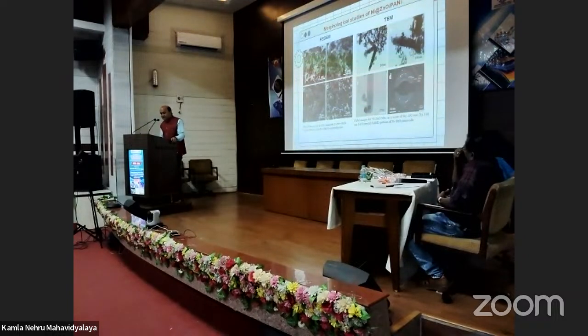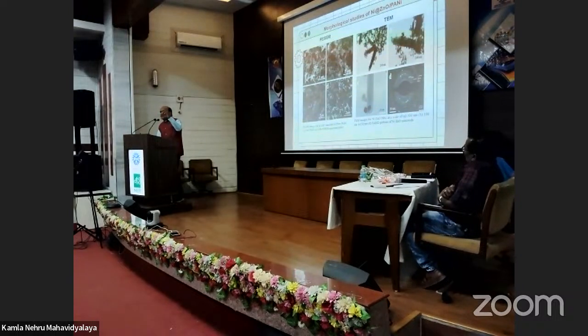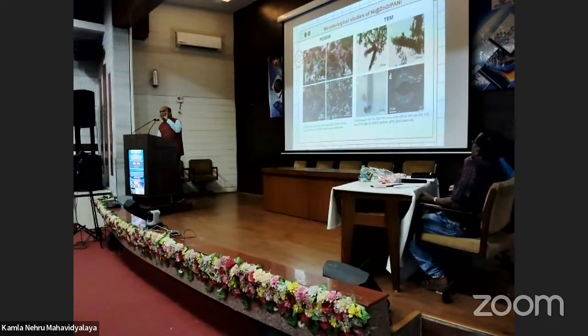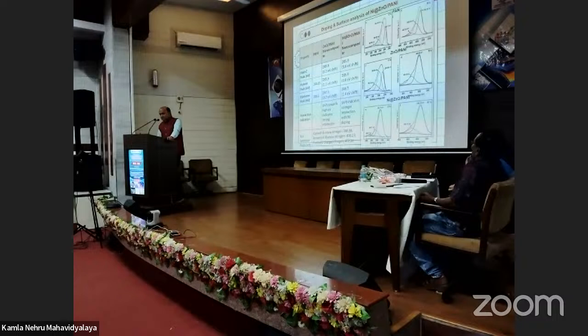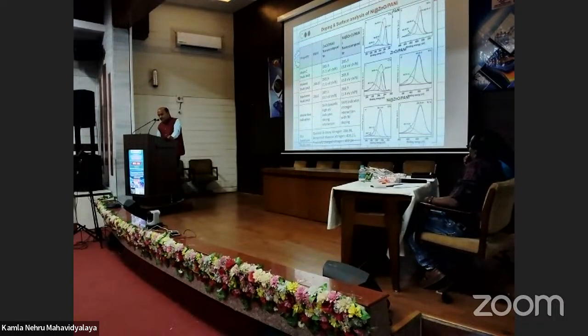This is the morphological study, field emission and transmission electron microscopy. If we look at the diffraction pattern, it seems to be a polycrystalline material, and the zinc oxide shows a rod-shaped morphology, and over the surface of the rod there is a decoration of nickel. Doping and surface analysis were done with XPS, O 1s and C 1s, and the rest, showing convoluted and deconvoluted spectra. With reference to this, the change in binding energy happens, and we observe that nickel doped zinc oxide polyaniline shows very effective convoluted and deconvoluted spectra. That is the oxidation state of that material.